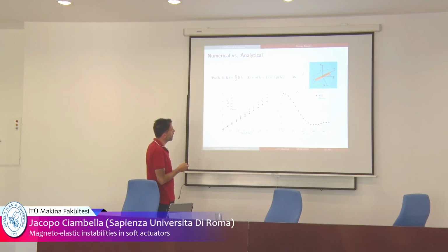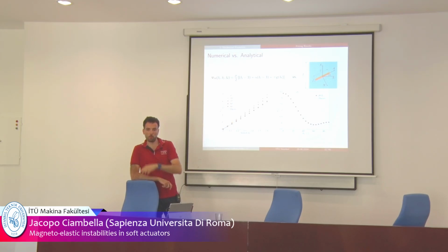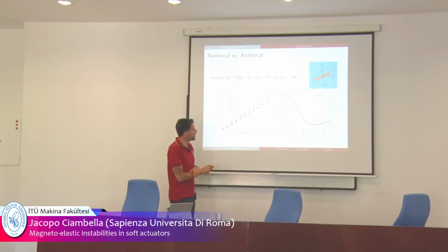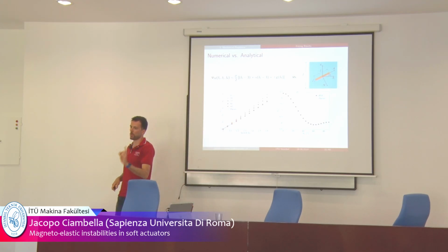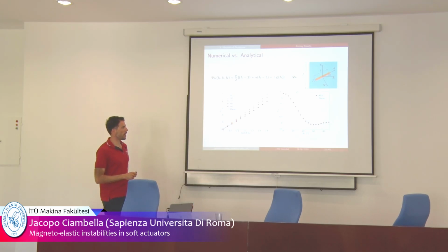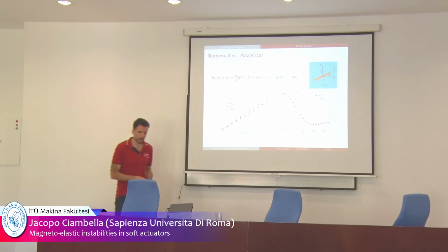And this is what you have. You have a very good agreement between the two models. Again, this was expected, but not so much, because, I remind you, the fibers are short and don't span the entire volume element. Interestingly, this is the Young modulus in the direction of the load, direction 1. So this is loaded in this direction, and this is the corresponding Young modulus. You have a maximum at 0 degree, as expected, but then the minimum is not at 90 degree. It's around 60 degree. This depends on the fact that we enforce, I believe, plane stress.